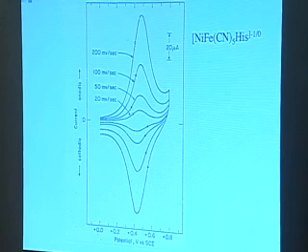We can change some of the ligands around the iron. Well, not some, one. After that, sort of the lattice falls apart. And here we put a histidine, a big bulky group, on, and show that when you do that, although the peak-to-peak separation still stays fairly small, and we can get a redox potential out of that, and we know it's on the surface, that the peak width increases. You'll notice you still have a linear scan rate dependence, but a wider peak.